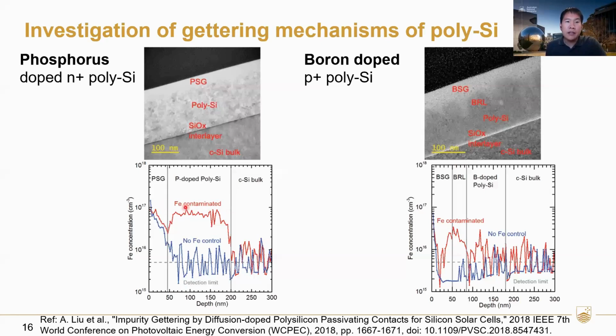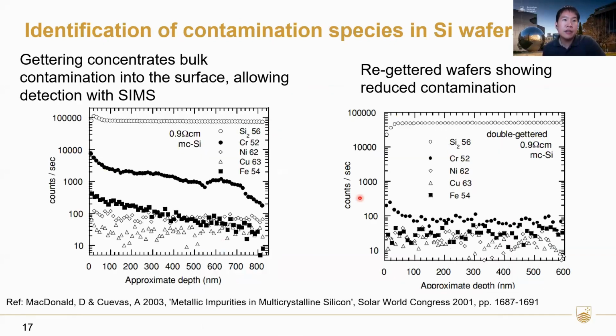We see that in the phosphorus-doped polysilicon, most of the iron is concentrated within the polysilicon layer. But if you look at the boron-doped polysilicon, we see that most of the iron is actually concentrated in a surface layer above the boron polysilicon, typically known as the boron-rich layer. So that's an example of the applications.